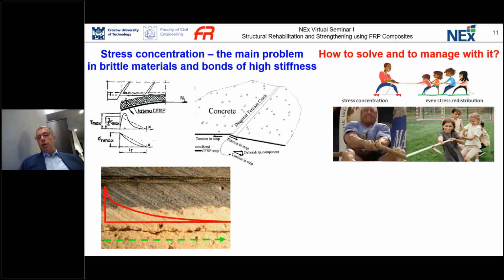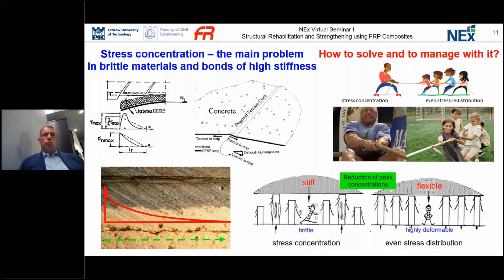It is very simple, because to avoid stress concentration, we should evenly redistribute stress. So in this case, we are able to protect the weak substrate, because evenly redistributed stress is, of course, of lower intensity. So if we bond two stiff and high strength materials or weak materials with brittle and stiff materials like epoxy resin, we can expect stress concentration. If we apply more flexible material, we redistribute the stress more evenly, and we can make more effective bonding in such applications.